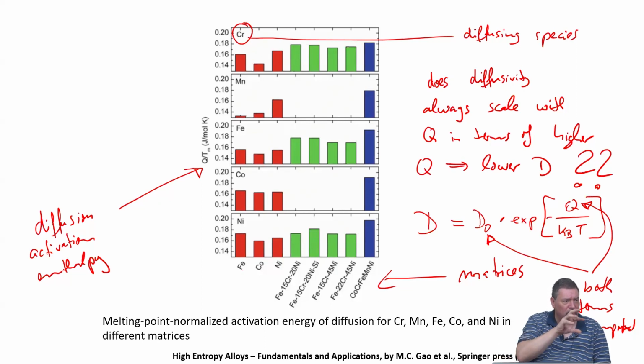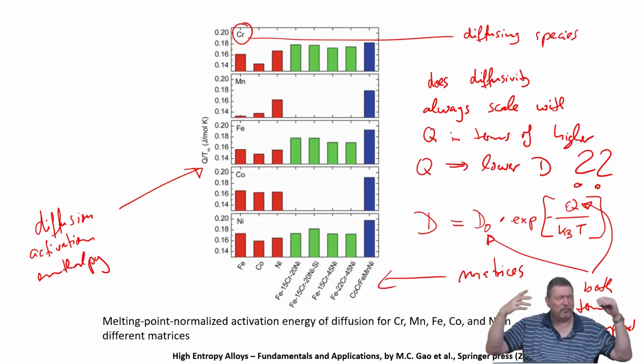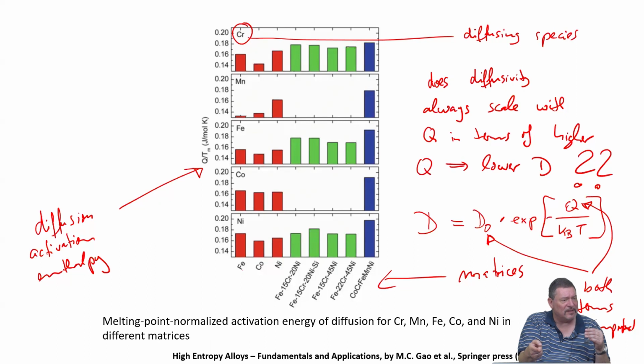So it means that even though a process has a higher activation barrier, so it should be slower, if it has also a higher prefactor and even much higher, then still the diffusion process can be faster even though the activation barrier is larger. This is specifically the case for some processes where, for example, in a substitutional diffusion process, the vacancy binds somehow to the atom which diffuses. So it means the process of the jump is quite large, but the vacancy will always be closely by. So the probability of finding an empty space is then very large. And this can then give rise to these counterintuitive relationships of having higher diffusivity even though the activation barrier is higher.